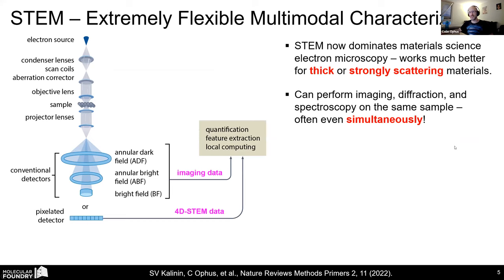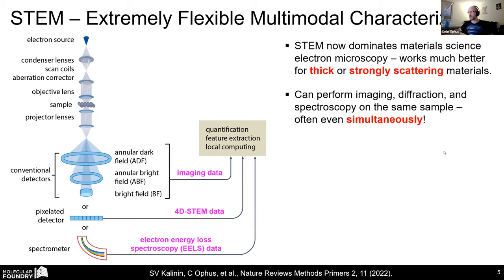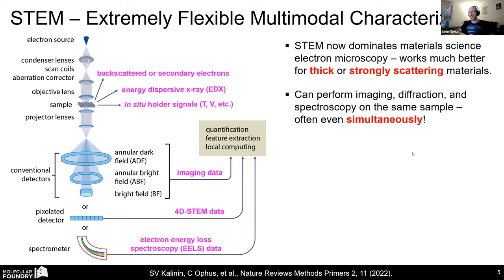More interesting to me, at least, is the advent of these pixelated detectors. And these were originally introduced primarily for biology to give much better electron sensitivity to measure biological nanostructures. But we use them to measure the full diffraction pattern of the sample. But I also want to call out spectroscopy, electron energy loss. You can collect backscattered electrons, secondary electrons, EDX signals, the X-rays generated by electron ionization events, and other in-situ holder signals. We saw a temperature measurement in a DENSsolutions MEMS holder in the previous talk.